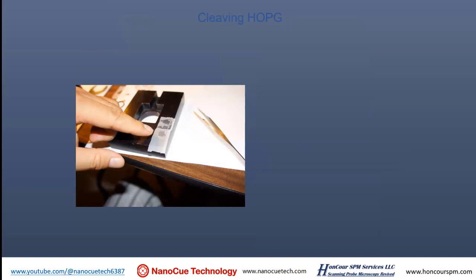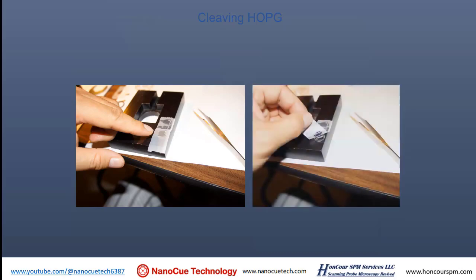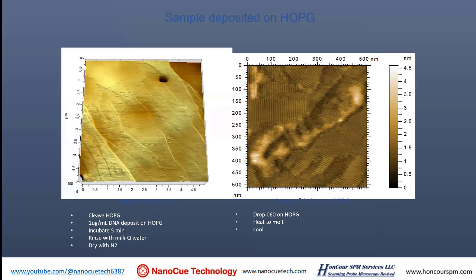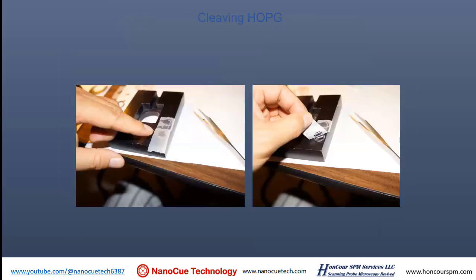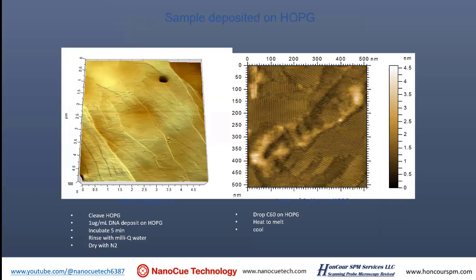Again, here's a couple of pictures showing the procedure to cleave your sample. You have a piece of graphite. Put a tape on it and peel off, and then you expose the graphite. Here's an example of the graphite after being peeled. The image on the left is the AFM image of this graphite. You can see these steps.